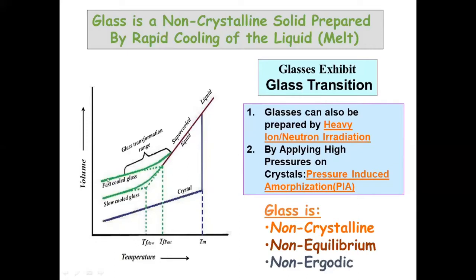So we can have a fast cooled glass, we can also have a slow cooled glass. And when you do this rapid cooling of the melt, the structure of the final glass is similar to that of a liquid, something which can flow. The structure of the final glass is very similar to the structure of the liquid, and they both have a disordered arrangement of the atoms. Whereas in a crystal, when you cool the liquid very slowly, you get a crystalline phase below the melting temperature. And whether you do fast cooling or slow cooling after the melting temperature or freezing temperature, you get the same phase.